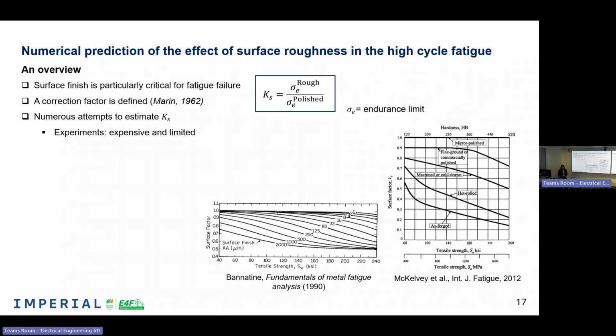On the one hand, we had experimental attempts. For example, in the 70s, they plotted these kinds of curves where they represented the surface factor as a function of the tensile strength for different values of the surface roughness. They were increasing the level of surface roughness, and they were measuring this using a lot of experiments. Or for example, in 2012, they also computed the surface factor as a function of the tensile strength, but for different surface finishes in the metal, in this case for steel. For example, as forged or hot rolled or machined, and they were relating more the type of production, the type of manufacturing with the surface roughness and the effect in fatigue.